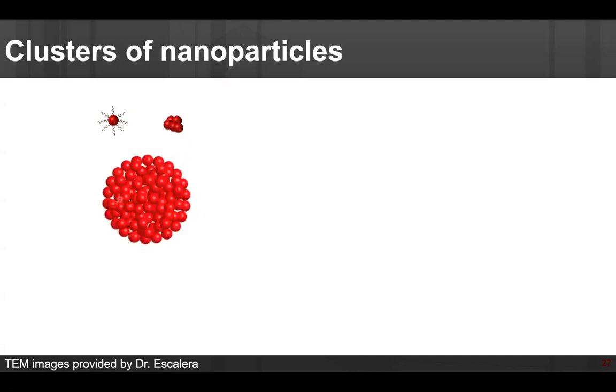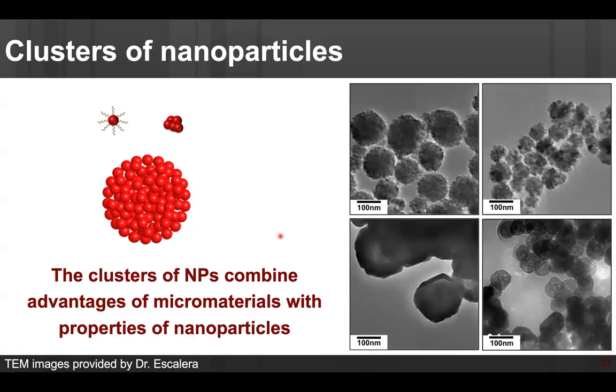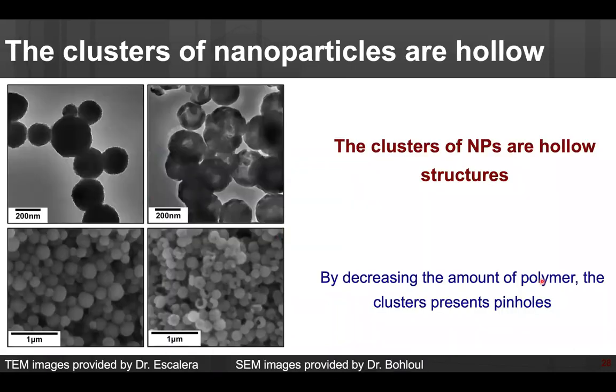For the cluster of nanoparticles, what we did was, let's use that agglomeration. Let's create a material where we define that agglomeration, where we can control how big the agglomerate is and that it is well defined. We can change the parameters and have clusters that are as big as 100 nanometers with individual nanoparticles that are like 5 nanometers, or clusters that are 100 nanometers but are made of nanoparticles that are 20. Or I can even make very porous materials with this synthesis. So I play a lot with this synthesis. I won't go through all the parameters that I move, but you can see that, for example, by changing the amount of polymer, I can break this interface a little bit, and I can see that my material is hollow.